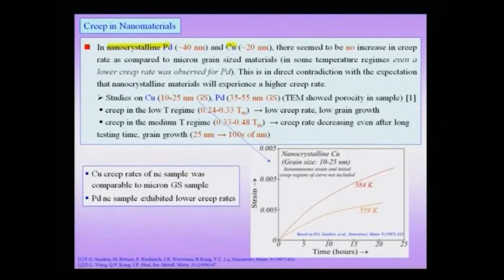So, if you talk about two important systems like nanocrystalline palladium and copper, which have been pretty well investigated, you can clearly see in these cases the grain size is of the order of 40 or 20 nanometer, which is extremely small. In this system there seemed to be no increase in creep rate as compared to the micron sized counterparts. This is pretty startling, that we did expect increased creep rate when you go down to nano sizes, but there was none. Of course, when comparing with micron size grain, we are using the same temperature for the comparisons.